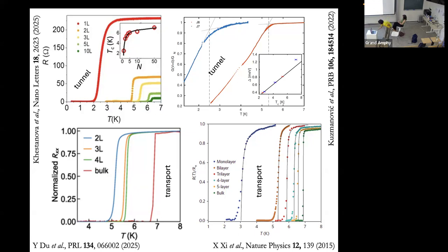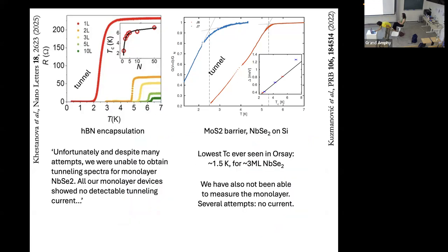Now I'm sure this is not the right figure because the next thing says that for Khestanova, unfortunately, and despite many attempts, they could never get tunneling spectra for monolayer NbSe2. So I'm sorry about this. The figures are all lower. And for us, also, we've never been able to measure the monolayer. We made several devices, and the lowest TC that we ever saw in Orsay is around 1.5K. I didn't have time to check last night if it's 1.2 or 1.8, but it's there. And it was about 3 monolayer, which is crazy.